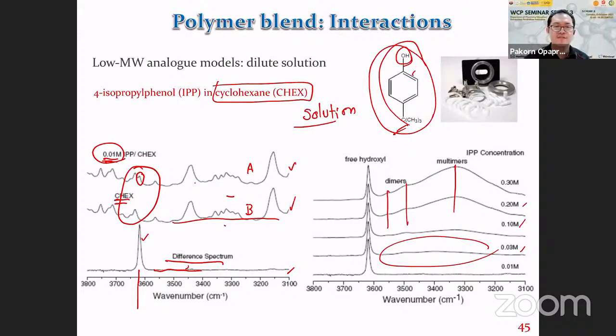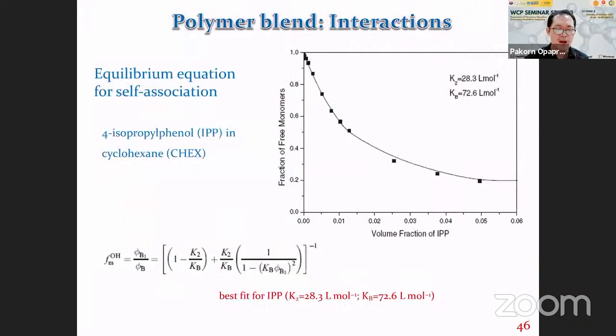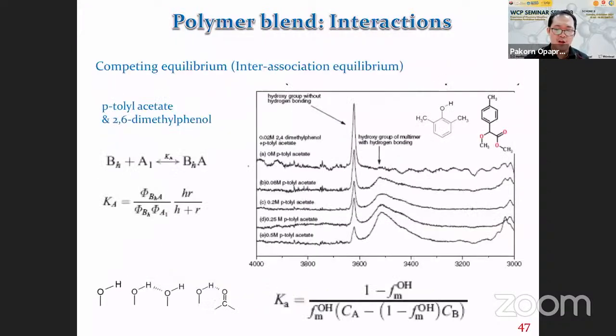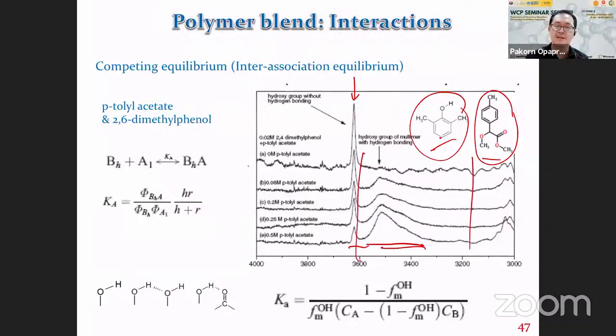So if we have this information, we can look at the nature of hydrogen bonding in the system by using curve fitting and the proposed equation here for hydrogen bonding. I will not go into the detail here. And also, if we apply 2 types of molecule together in the solution, this is the spectrum that we can get. Again, we have free OH peak right here, and then hydrogen bonded peak in this region.